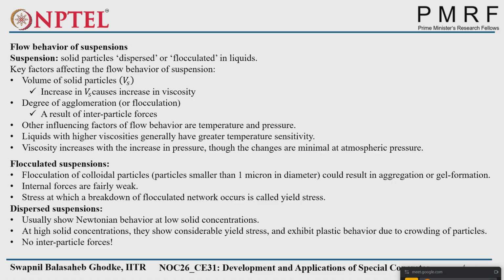Then flocculated suspensions. Which type of suspension do we call flocculated? Particles smaller than 1 micron in diameter could result in aggregation or gel formation. In the case of flocculated suspensions, internal forces are fairly weak, and the stress at which the flocculated network breaks down is called yield stress. So, in which case are the internal forces fairly weak? Which type of force? Which type of bonding? Van der Waals force bonding.